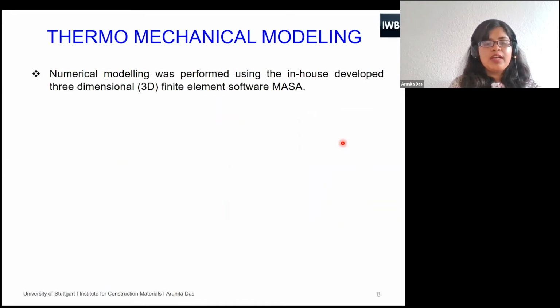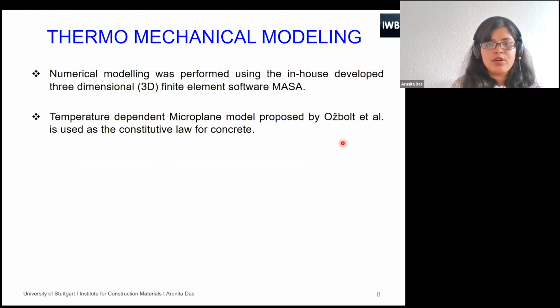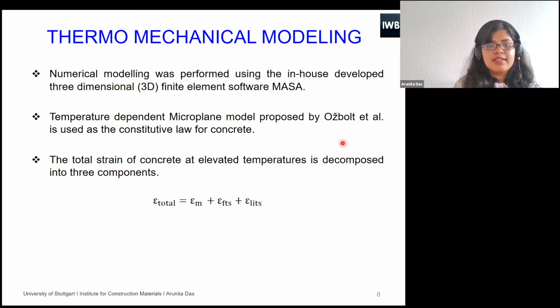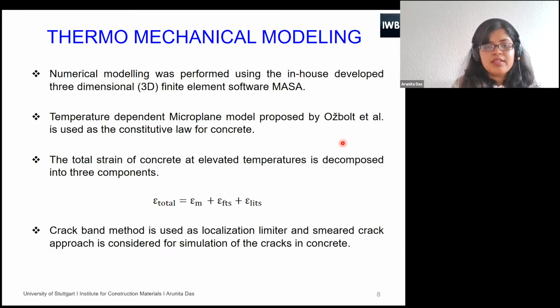So, thermomechanical modeling, how I have modeled the structure. All the numerical investigations are carried out using our 3D finite element software, which is our in-house software called MASA. Here, the temperature dependent microplane model, which was proposed by one of our professors, Professor Ožbolt, is used as the constitutive law for concrete. In this case, the total strain of concrete at elevated temperature is decomposed into 3 components: mechanical strain, free thermal strain, and load-induced thermal strain. Then the crack band method is used as a localization limiter, and the smeared crack approach is considered for the simulation of the cracks in concrete.